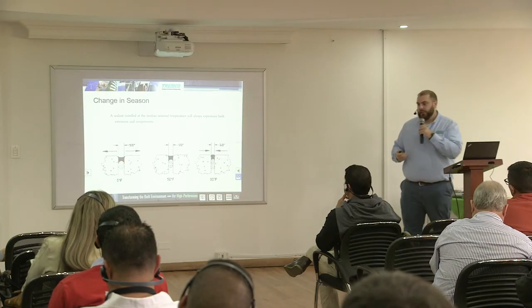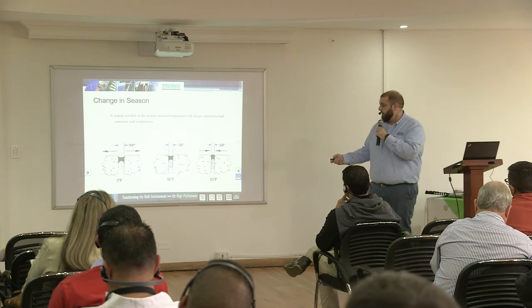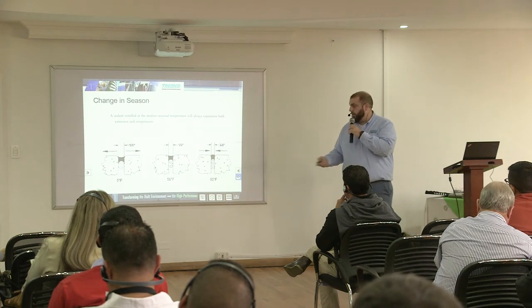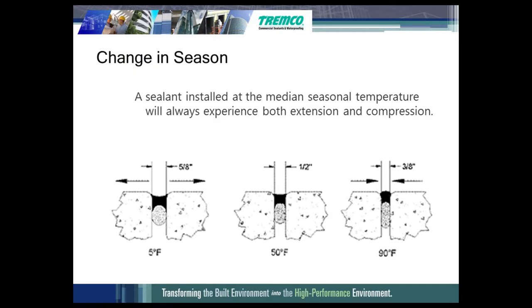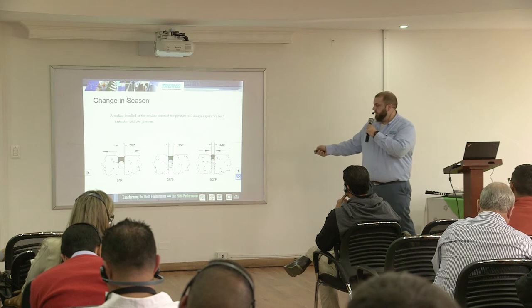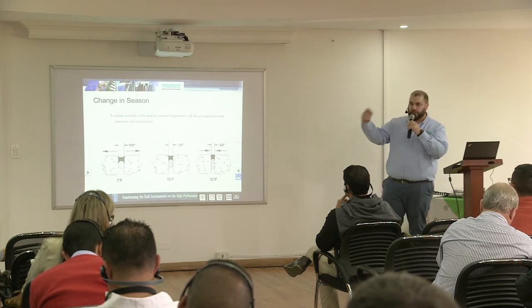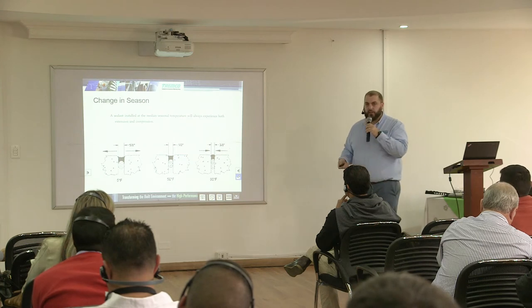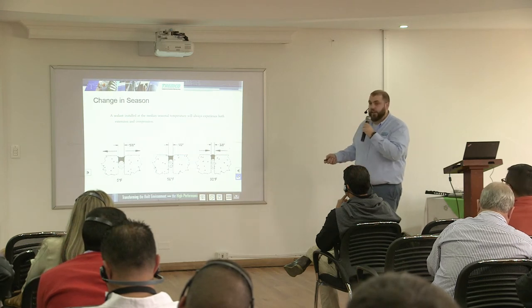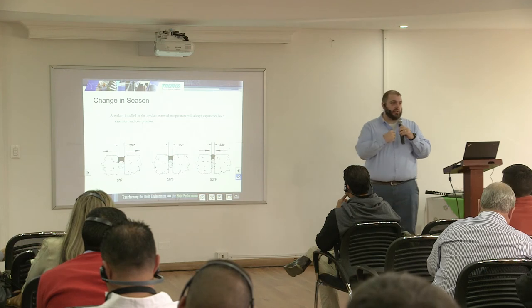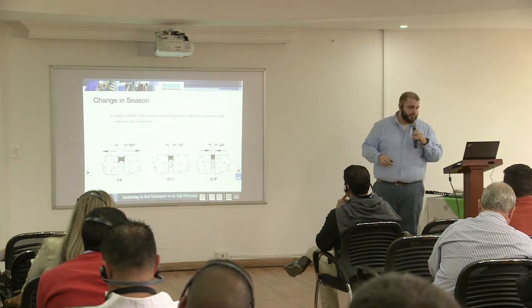Otherwise, if you install your sealant at this largest joint width, your sealant is then in compression the rest of its life. If you install the sealant at the warmest temperature, the sealant is then in extension the rest of its life. What that means is, if it's in compression, you develop what we call bread loafing, where it sticks above the joint and it wears a lot faster. If it's in extension, the sealant is seeing a lot of stress on that bond line and it's pulling.